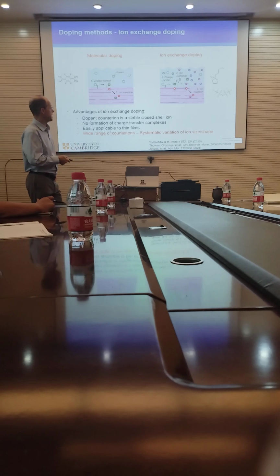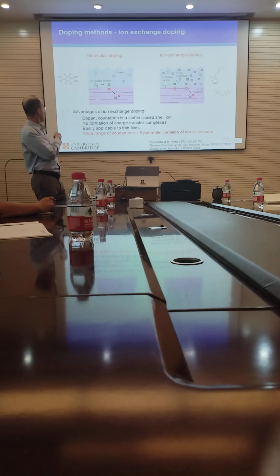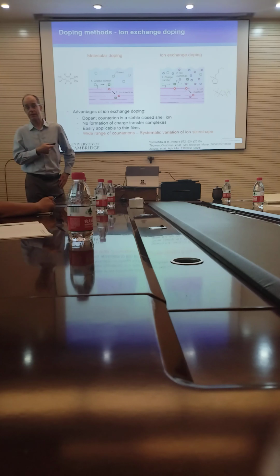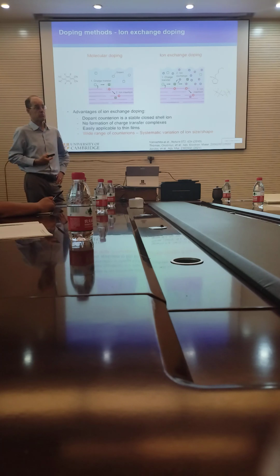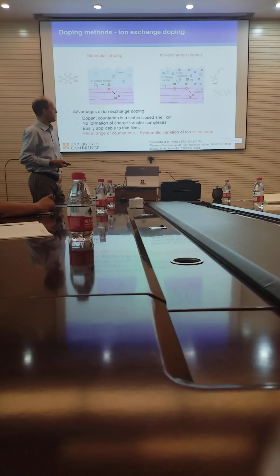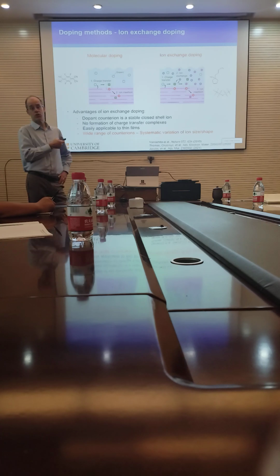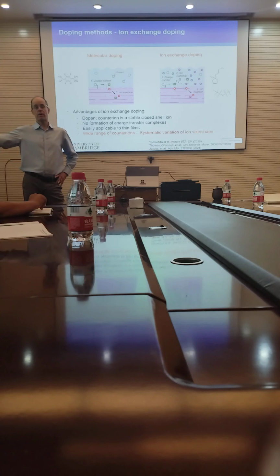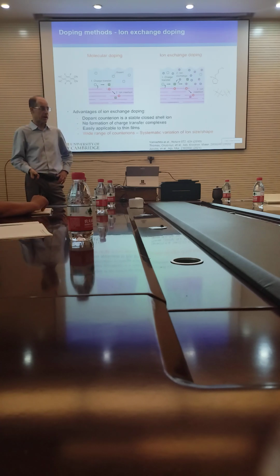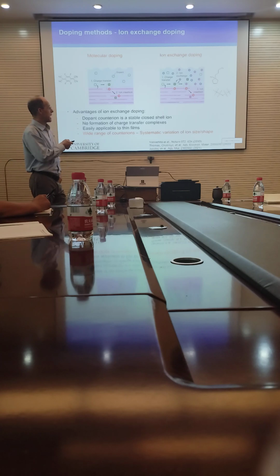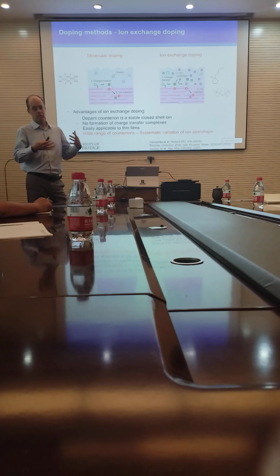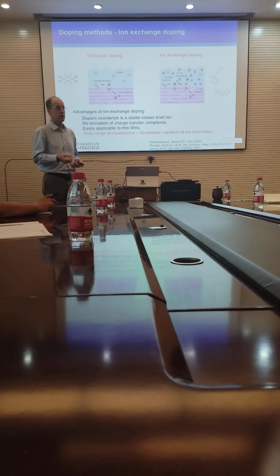And that's an advantage because the ionic liquid anion is more stable than this radical ion that you would generate in molecular doping. And the other advantage is that you can choose that ionic liquid anion from a wide range of anions. You can basically run through the catalog, order lots of ionic liquids, and then look at, for example, how the conductivity depends on the size or shape of your counterion.